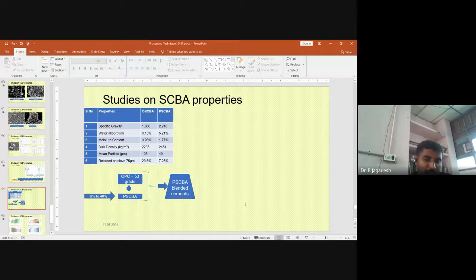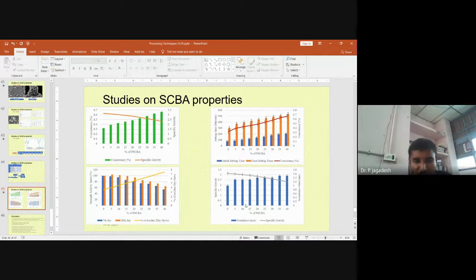Then it is blended with cement. The property of cement is shown in this slide. With increasing PSCBA content, you can see there is an increase in strength. I had gone for 40% replacement of ordinary Portland cement of 53 grade.